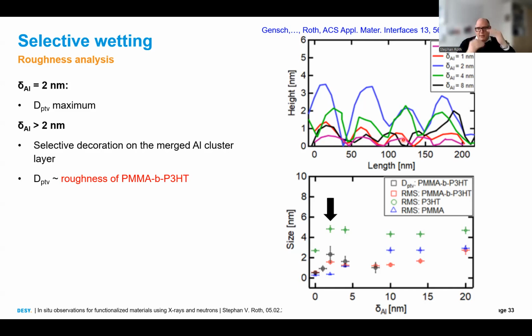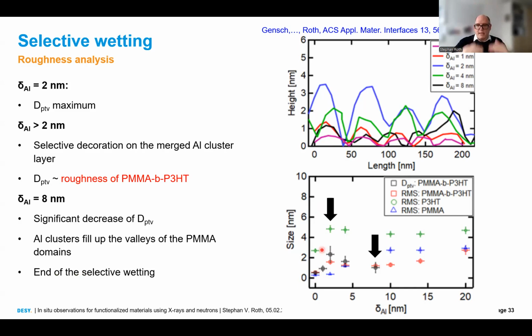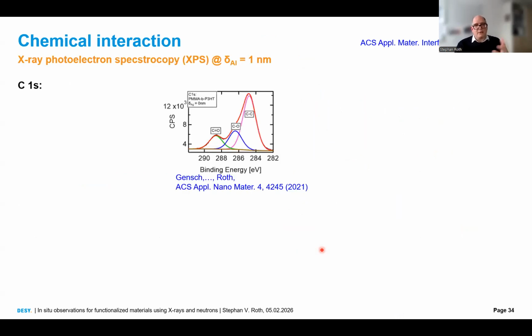And if you look at the distance of peak to valley, you can plot this here, and you see that this peak to valley first increases, aluminum selectively grows on one block, and then it goes down again, because then the aluminum goes also to the other block. And then you have the growth of aluminum, and these two growth modes touch each other, and you finally have a full aluminum layer. Good. This is with AFM, and you can confirm this.